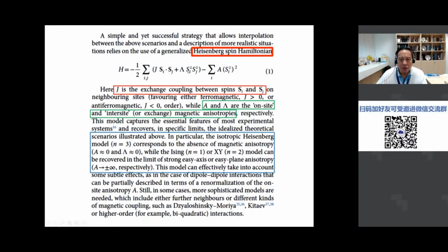And it turns out that for the isotropic Heisenberg model, that's n equals 3, where you have an absence of magnetic anisotropy, A and Λ are about 0. Hence, that's why you can't get magnetism. But in the Ising or the XY model, n equals 1 or n equals 2, in the limit of strong easy axis or easy plane anisotropy, where A tends to plus or minus infinity, it's non-zero. This model can take into account all the effects that show some kind of long-range order. Okay, so this is a Hamiltonian that governs 2D magnetism.